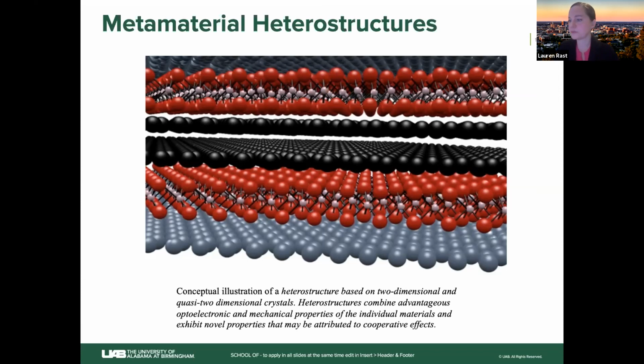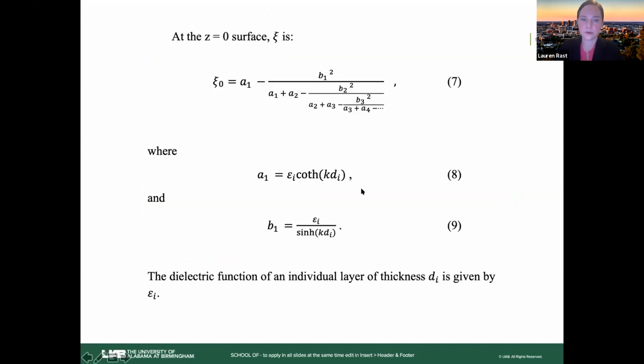So as we mentioned before, these hybrid plasmonic materials are good candidates for high Q factor plasmonic materials. Those that contain metal and a combination of high and low refractive index materials exhibit longer propagation distances. Okay, so this is one way to model these heterostructures. It's a classical model, and it works within the regime that we tested it for. I'm going to say a little bit about limitations of this type of model later on. But this model is very, very efficient.